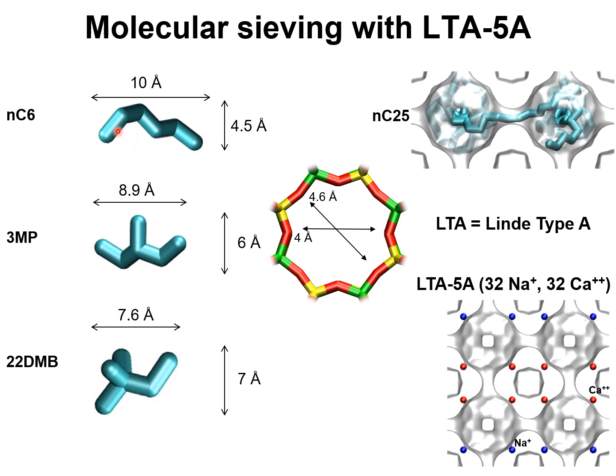It is possible for a linear molecule such as hexane to diffuse easily, or relatively easily, through the 8-ring windows of LTA-5A zeolite, whereas the monobranched isomer and the dibranched isomers are limited in their ability to hop from one cage to the adjacent cage because the dimensions of the molecules prevent the intercage hopping.